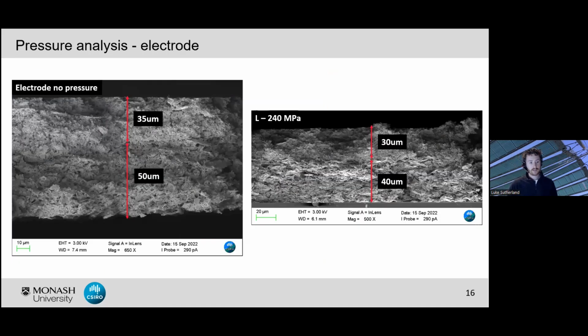If we look at the electrodes under the SEM, we see we do get slight compression of the electrodes going from about 50 micron to 40 for our carbon and about 35 to 30, maybe a little bit less for our silver. Now this was shown to also improve the conductivity of our electrode film. Interestingly, the carbon film actually reduced in conductivity, but the silver film significantly improved in terms of electrical conductivity, which then led to almost twice the conductivity with our pressed electrode.